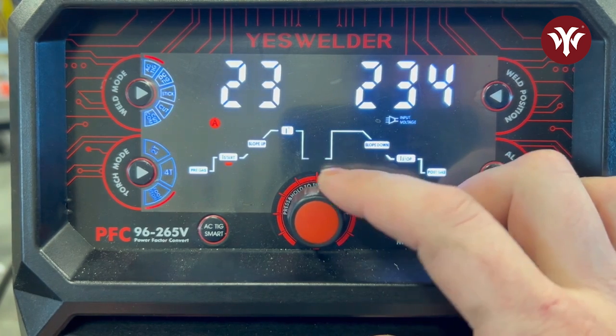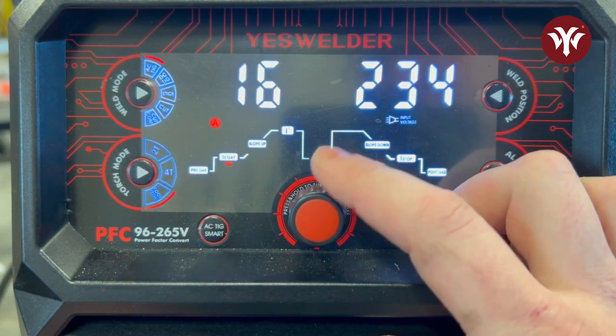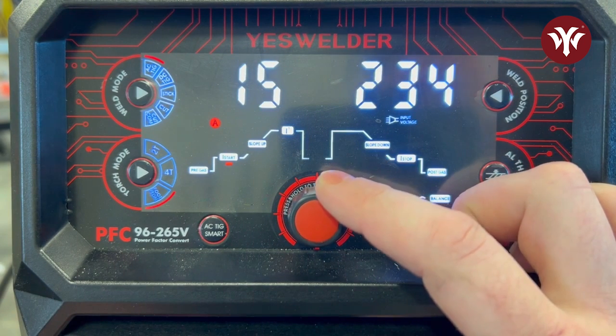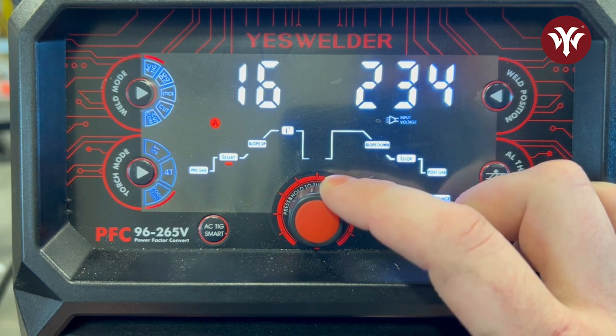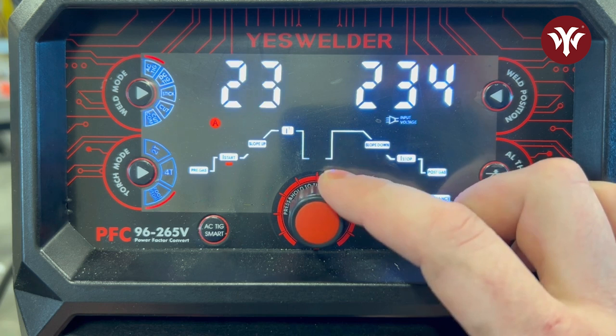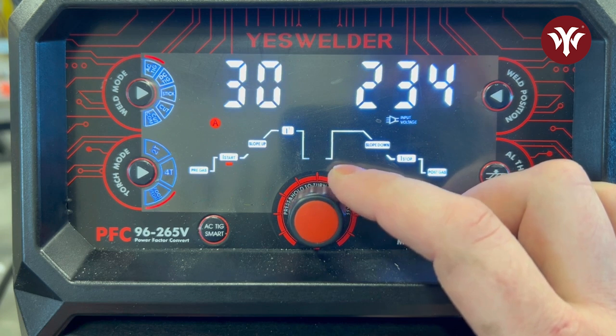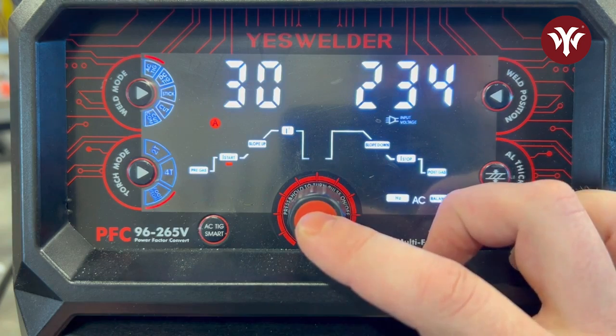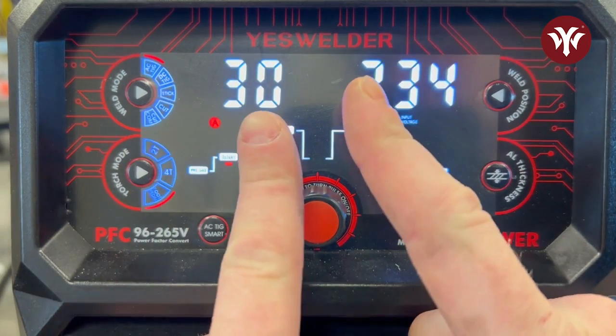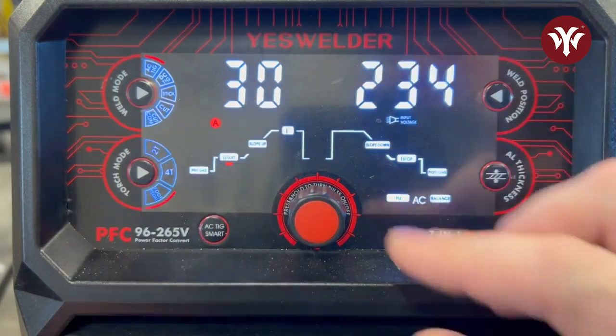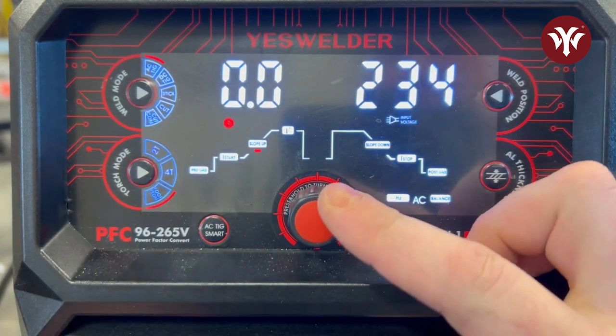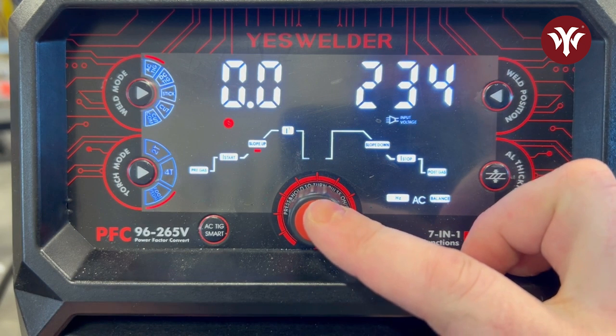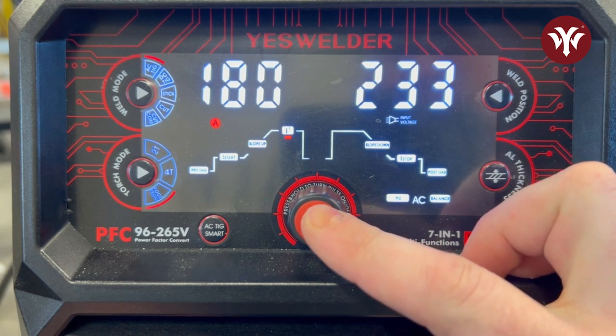When I clicked on this initially, it was set at 15 amps. That's a default. I have noticed that the pedal is more sensitive than what I was used to. So since we're welding thicker, well, not thicker, but welding 1/8, I'm going to turn that up to about 30 amps. And that should bring the effective control zone of my pedal closer together. Slope up is 0 seconds, okay? So it's going to go from starting current to full adjustment.